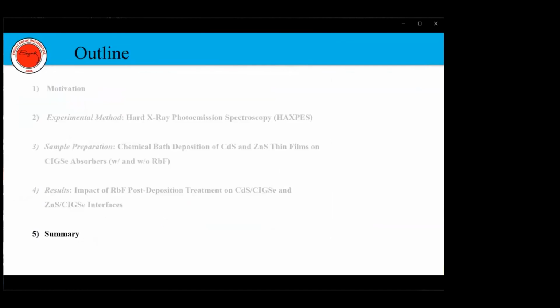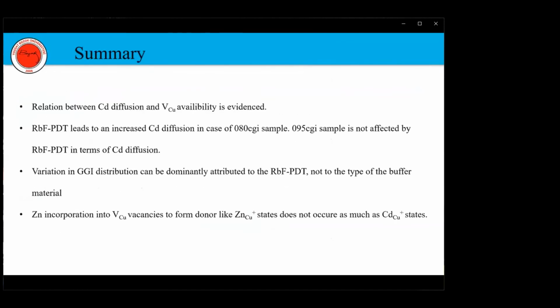With this, I would like to summarize our findings. We found a strong relation between cadmium diffusion and copper vacancy. We found that rubidium fluoride post-deposition treatment leads to an increased cadmium diffusion in the case of relatively copper-poor samples. The copper-rich sample is not affected by RbF PDT in terms of cadmium diffusion.